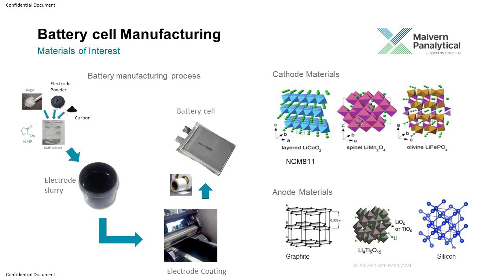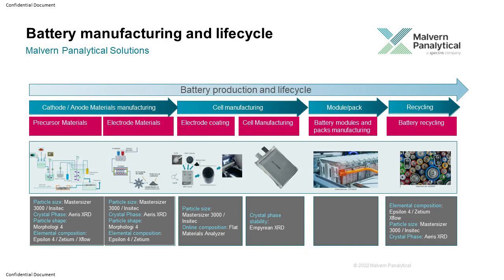So it is not a safe kind of material. So it is still in R&D, but there are some breakthroughs that either mixing with graphite or making it porous kind of silicon that even if it expands, there is a space for that. So in the next 3-4 years, most likely silicon will replace the graphite.